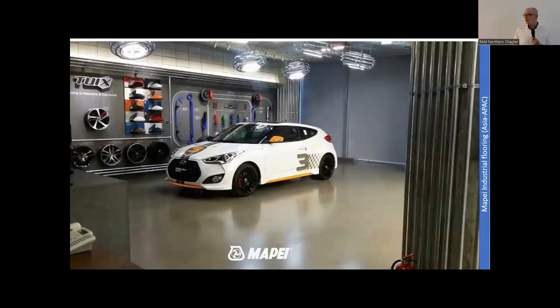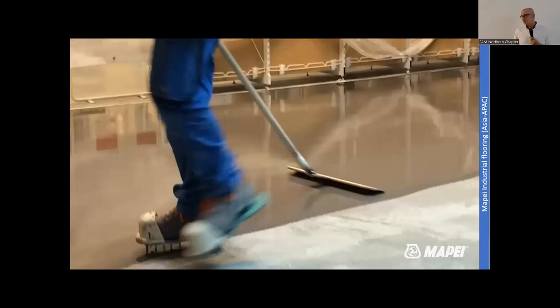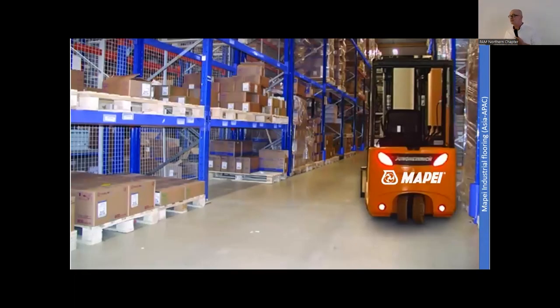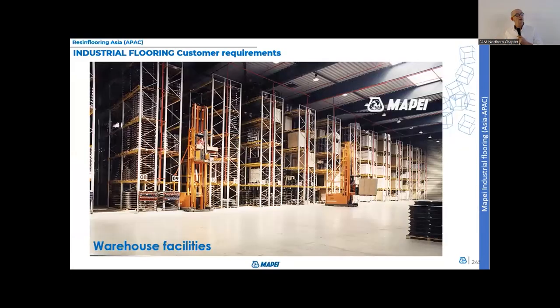In this case, it is a showroom. The material is pumped onto the floor either by the machine you saw earlier, a pumping machine, or we can use it by hand. We float over it with a shuttle, and that's basically it. So it makes it quite user friendly for heavy duty forklift, as well as leveling to a certain extent, maybe not super flat, but it levels extremely well to category 2 or FM2. So according to the standard, if I have to adjust, I adjust only a little bit. But this material can really withstand the traffic, the compressive strength, and the leveling.